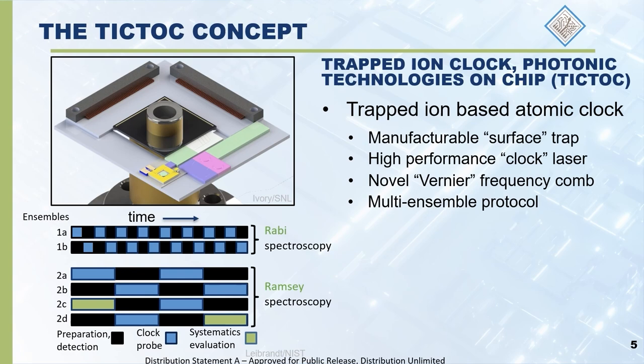And tying the whole enterprise together is the multi-ensemble clock protocol. By probing the roughly 30 ions trapped in the device in a particular way, we can achieve a better than standard reduction in noise, allowing the system to hit the target stability metric.